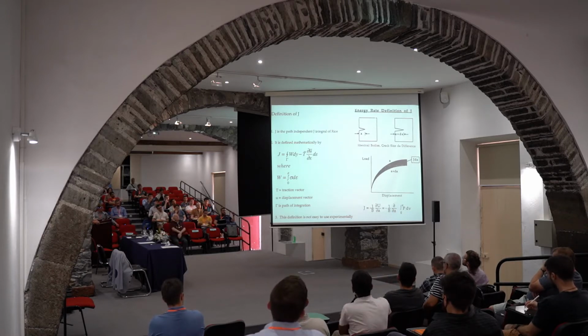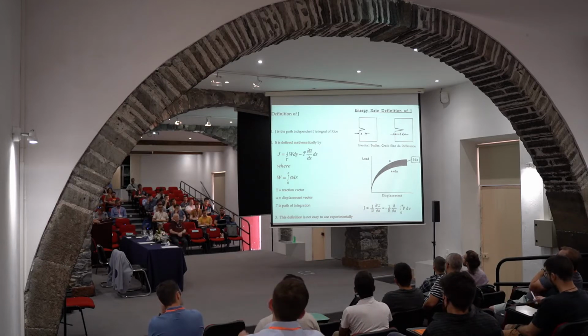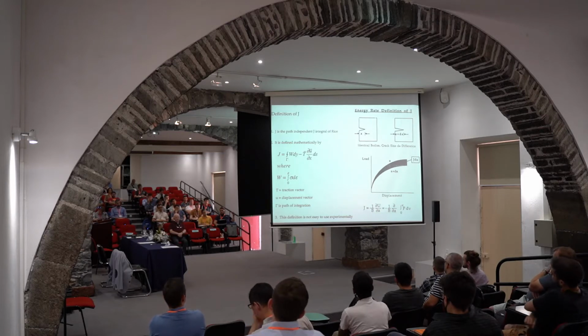And you can see, I guess, at once that it's not easy to use such a definition for experimental measurement. If we compare it with crack tip opening displacement, it is just the geometry, and you can measure it easily. In this case, you will see how actually it was measured, but it's definitely not directly seen from this equation. This equation comes from the continuum mechanics principles, and I will show that later on.